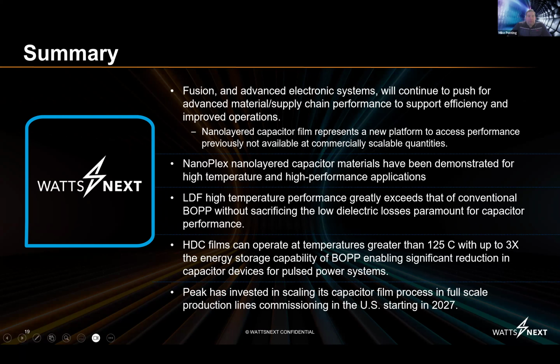Just reminding you again, Nanoplex is a unique approach to making new kinds of capacitor films. It's real similar in how you make standard energy storage capacitor films. The only twist on it is that you're putting these nanolayers, in tens, hundreds, or thousands, inside of the thin plastic film. And that has enabled two unique flavors of capacitor film, either low dielectric loss, LDF, or high dielectric constant, HDC, capacitor film to be created, demonstrated, tested, and integrated into some applications here in the US. And it is slated for full scale up and production as the first US-based capacitor film manufacturer starting in 2027 when our equipment is commissioned.